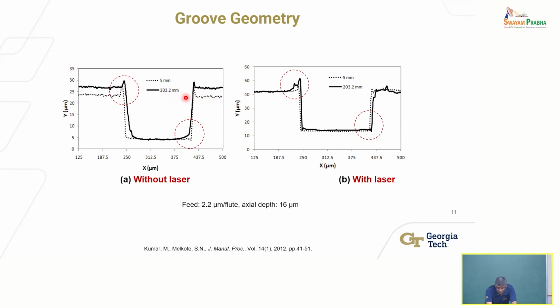And that's there for both cases. But you can see deviations from the squareness of the groove as you keep cutting, because the tool is wearing. And you will look at the tool wear, and that's what happens. This is without the laser. This is with the laser, okay? And here you can see that, yes, there is some burr formation. It's not zero, but it's less. And even after 203 millimeters of cutting, it's more, obviously, than before, but you can see here the geometry is much more accurate, right?